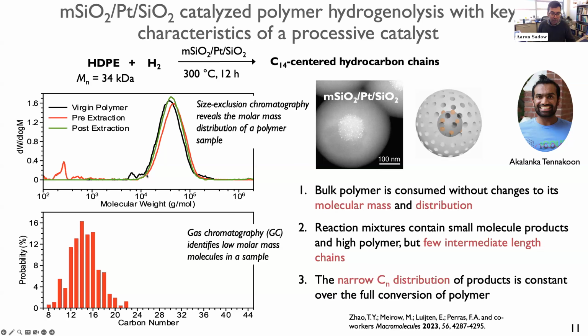So in this top plot, these are the size exclusion chromatography curves of the starting polymer. That's the black one. Then we do hydrogenolysis of the polymer and convert about 30% of the mass into things that aren't starting material. And that's this orange curve. And then we extract away those soluble species, and what remains behind is the green curve.